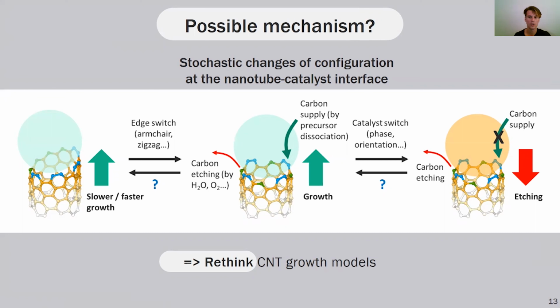cannot explain the presence of etching. It should lie in the chemical potential faced by the nanotube. One possible explanation is the existence of different phases of the catalyst, for example, a metallic one more active and a carbide one less active, which is also possible, but to prove this theory, more TEM experiments in realistic conditions are required as well. And in any case, it's necessary to rethink current carbon nanotube growth models.